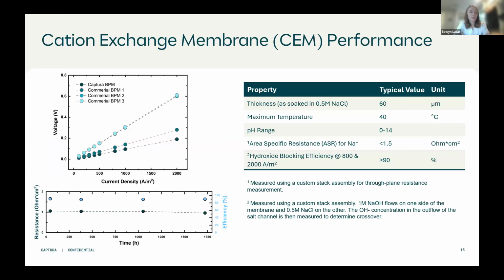So we can produce similar tables here. If you take that area-specific resistance and multiply it out across multiple different current densities, you can see what the voltage characteristics would be. So basically what the voltage that individual membrane will contribute to your overall stack will be. And again, you can see here, Captura has been able to develop a very conductive cation exchange membrane option. And as far as the resistance, it's improved over other commercial membranes that we've worked with.